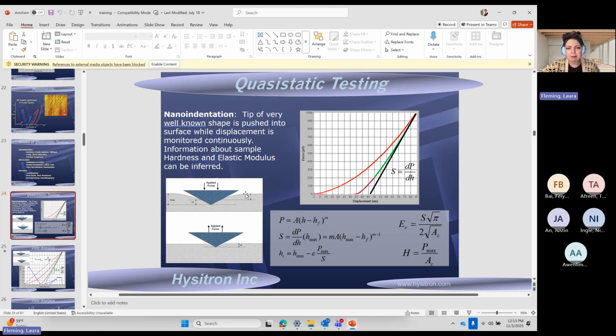So we have this probe that is being pushed into the sample, and from the force and displacement information we get out of the transducer, we're able to then calculate hardness and modulus. So we have this loading and this unloading. We then do a power law fit to the unload. And when you take the first derivative and fit at the maximum, you get the stiffness of the material. From that stiffness, we get a lot of other information. So where that derivative intercepts the x-axis is what's known as our contact depth, which we will talk about quite